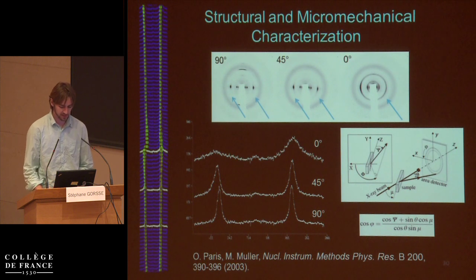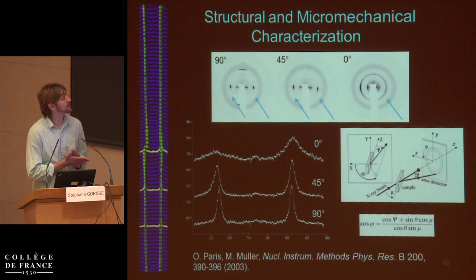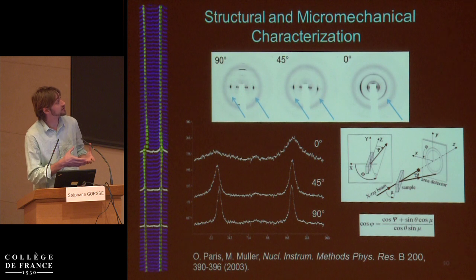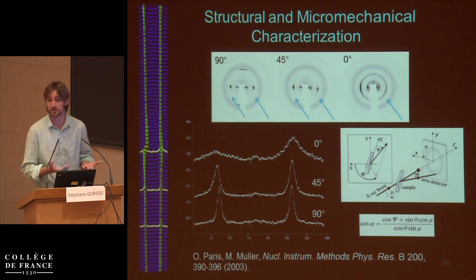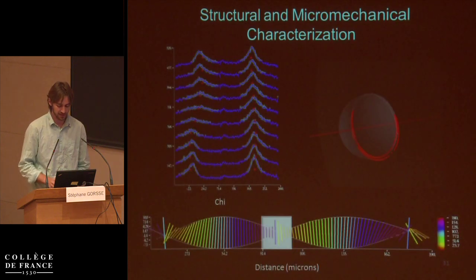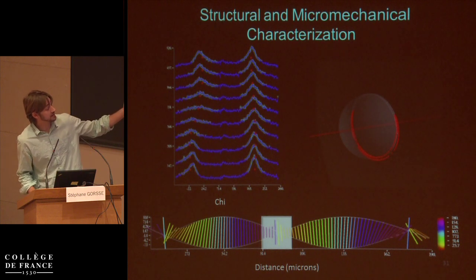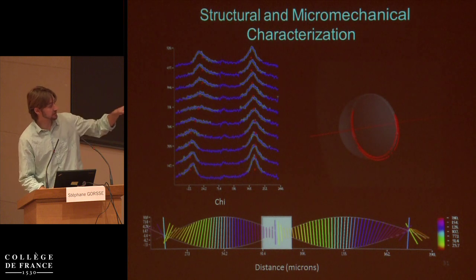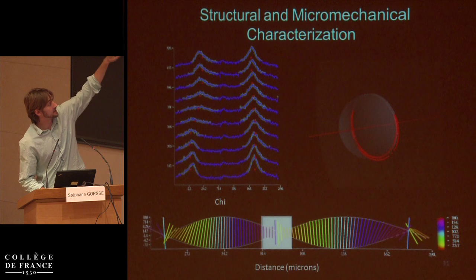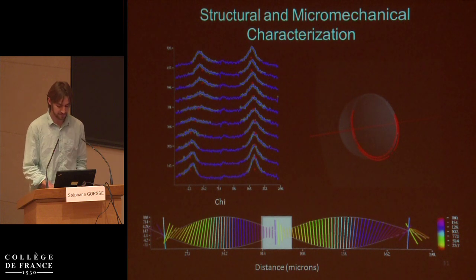And using some work developed by Helga, and then later further developed by Paris and Mueller, you can actually calculate the angle of a fiber from a single diffractogram in 3D space. And we can make a reconstruction then from all of these diffractograms and reconstruct the entire helicoid, right up until the fiber gets a little bit too close to the beam, which is what you're seeing in that white box, and the technique breaks down.